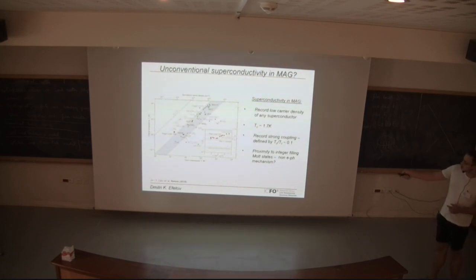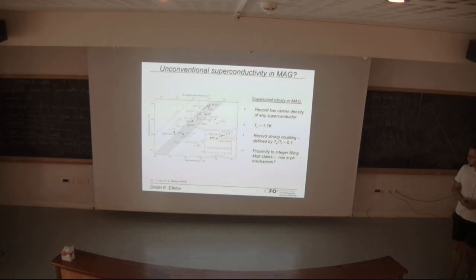And basically, what this Moiré plot tells you is that the closer you are on this diagonal line to Tc equal to Tf, so the closer you are in that direction to that solid line, the stronger the coupling of the underlying superconductor is. And as you can see, magic angle bilayer graphene on those energy scales is basically close to all the high temperature superconductors we know. So here, for example, we have the cuprates, and if you can see here, magic angle graphene is actually even closer to this diagonal line than these superconductors.